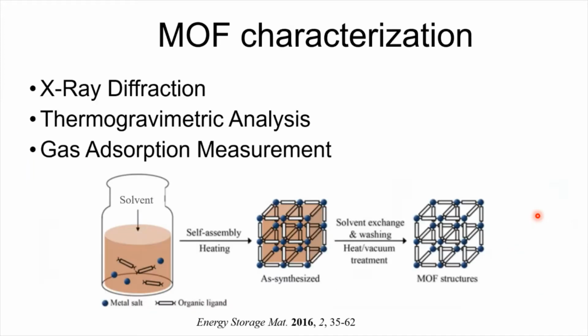How do you characterize them? I would call these the three essential methods of characterizing. There's really more, but these three are the most important ones, where you have X-ray diffraction, either single crystal or powder, thermogravimetric analysis, and gas adsorption measurement. And I have down here this scheme of synthesis, where we can go through each of the steps. So once you make your material, you want to know the structure that you have. And that's when you use single crystal X-ray diffraction. Now, if you already know the structure and you just want to compare it, then you use powder X-ray diffraction. That will instantaneously tell you if you have the corresponding structure.